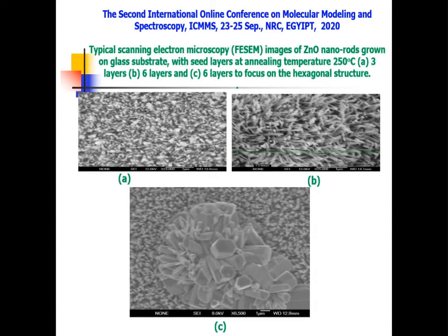To study the effect of the seed layer under the zinc oxide nanorod, we prepared two films, one with 3 layers of seed layer and the other with 6 layers. We can see well that the rods in A with 3 layers are smaller than the rods deposited on the 6 layers of the zinc oxide seed layer, and we focus on the hexagonal structure in figure C by enlarging a small area to see the hexagonality, the homogeneity, and the good alignment perpendicular to the substrate of the nanorod prepared.